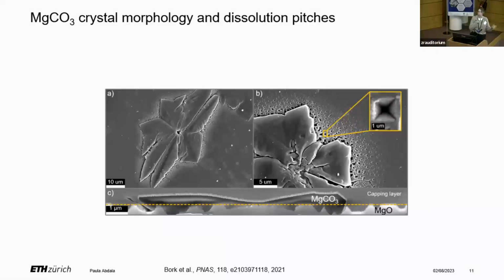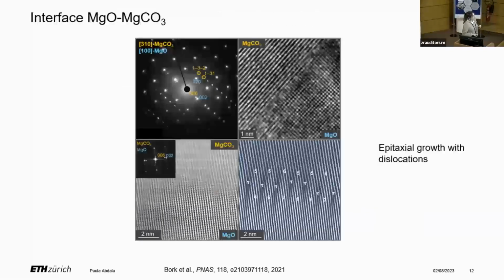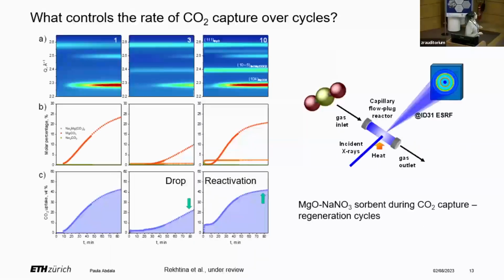Very well. So we knew that it was at the buried interface, and we washed away the sodium nitrate, and we could, in fact, visualize the crystals that were grown underneath the sodium nitrate. Further, Elena Willinger cut a lamella and could see that the magnesium oxide and magnesium carbonate are really close, and there is certain coherence between these two crystals. So we learn where and how magnesium carbonate forms.